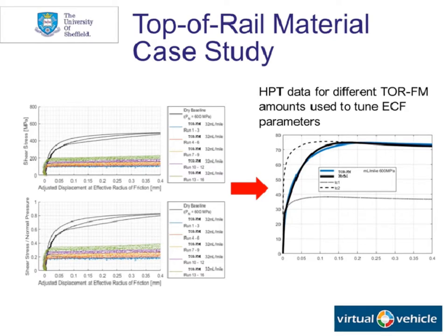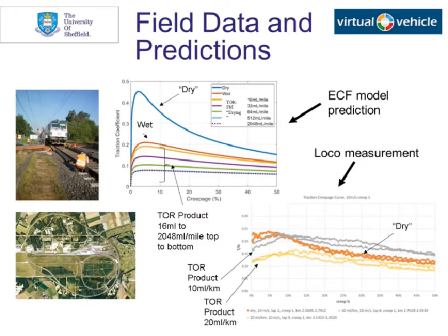We did lots of tests with lots of different amounts of product. You can see one particular amount here. And the data is showing what happens as you progressively cycle over and do different numbers of cycles over the product. The black line at the top obviously being the dry value. So here you can see we're getting a friction coefficient somewhere between 0.2 and 0.35, which is very typical of a good top of rail product. This data collected from the HPT testing was used to tune the ECF model and create a parameter set we can use to then carry out predictions for other types of contact. And that's what we did.